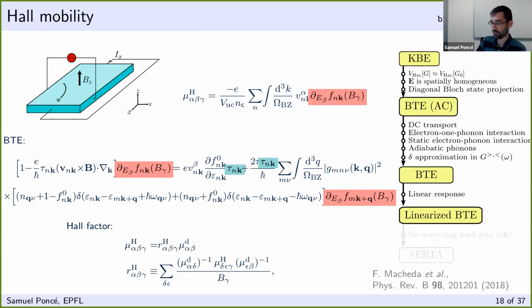And this was not giving very good results, but very recently, Yun-Jun added basically this commutator, and therefore this is a second way to compute the velocity, which does not depend directly on the Wannier function, and that converges a bit faster. However, this is not shown in the result because this is very recent. But yeah, so those are basically the two ways to compute the velocity.